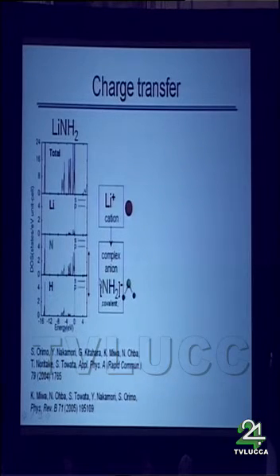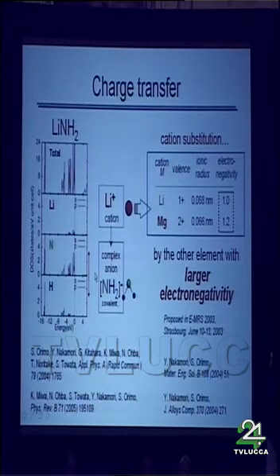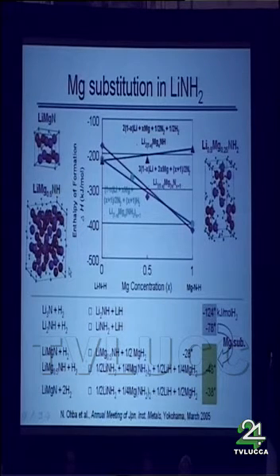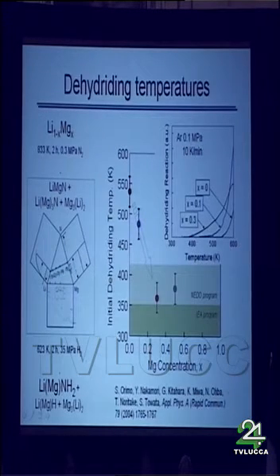to stabilize the NH2 clusters. That's why we have proposed that the partial substitution of lithium by another element with larger electronegativity, like magnesium, is an effective way for destabilization. I will not go into detail, but this proposal was reasonably supported by precise calculations. Based on the proposal, we have synthesized some samples, for example, starting from lithium-magnesium alloys, then nitrogenation, and then hydrogenation. It was hard to produce a single phase of the substitution, especially in the case of magnesium. But we could prove that the initial dehydriding temperature is decreasing with increasing magnesium concentration, down to 317 Kelvin.